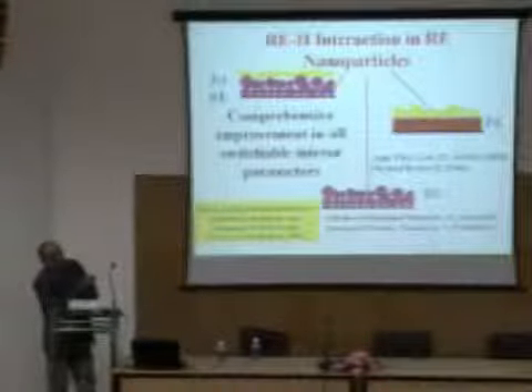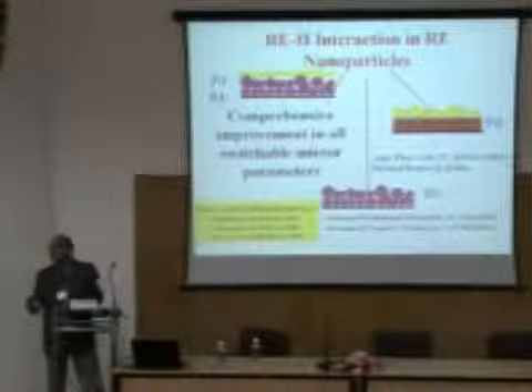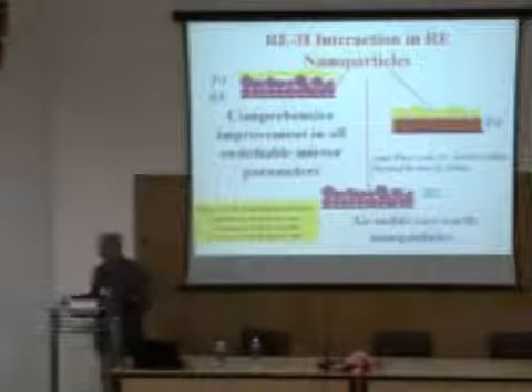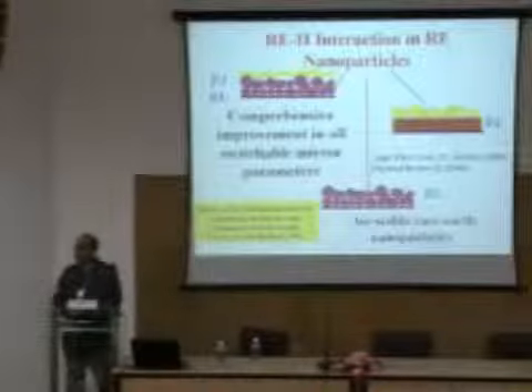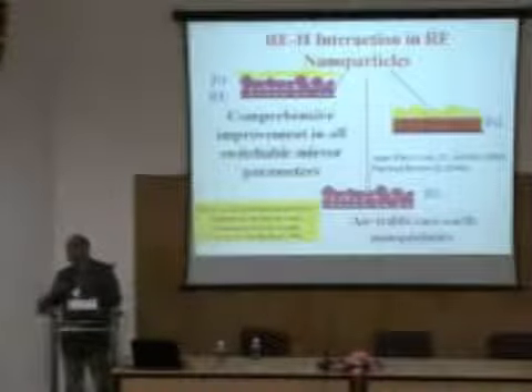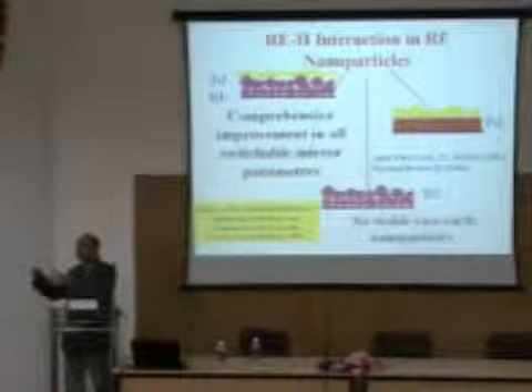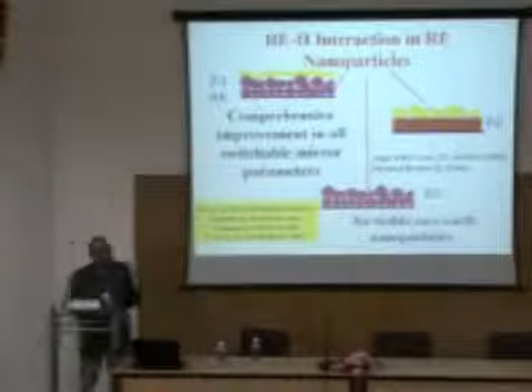So what we did, we removed the palladium cover. We exposed these nanoparticles to oxygen and then investigated the properties. And to our surprise, these nanoparticles were stable in oxygen. At least their stability was much better in comparison to thin films and bulk materials. So this was a very, very surprising result. But now we understand why it is happening.